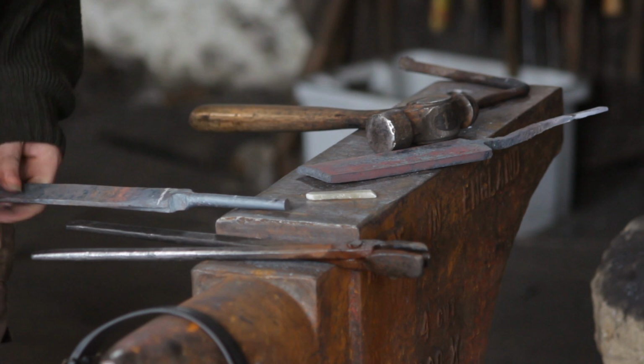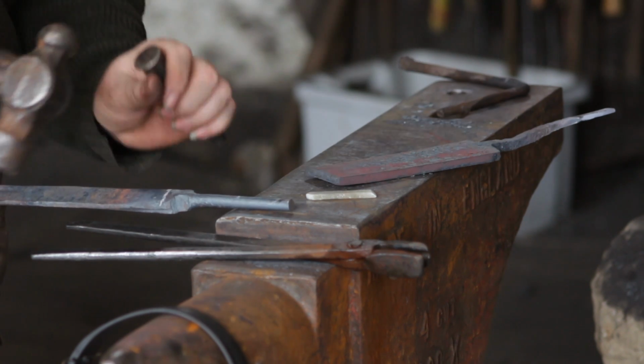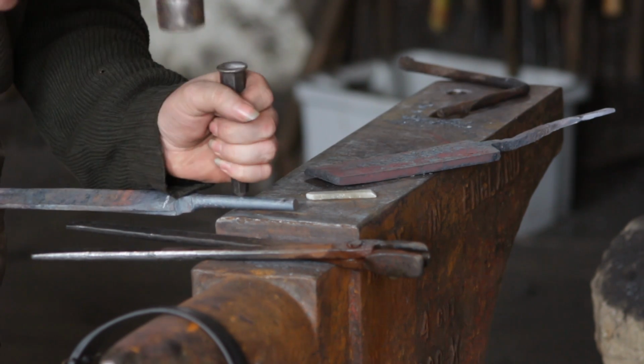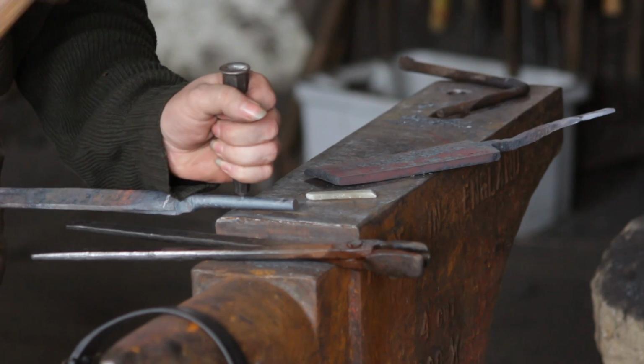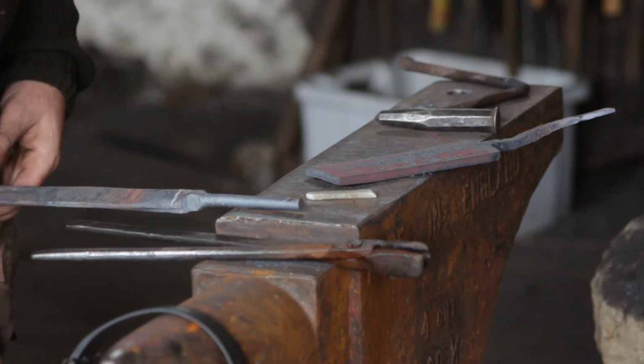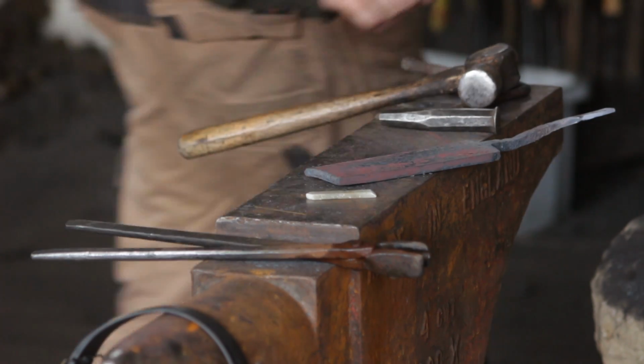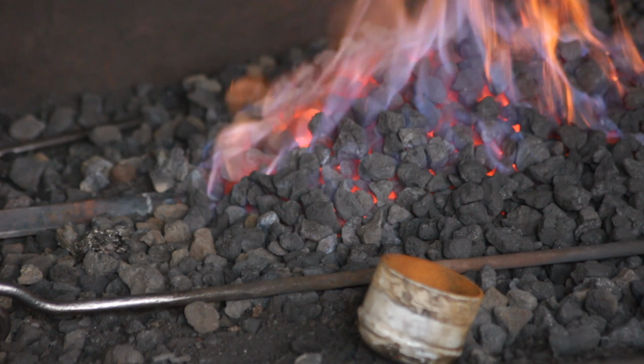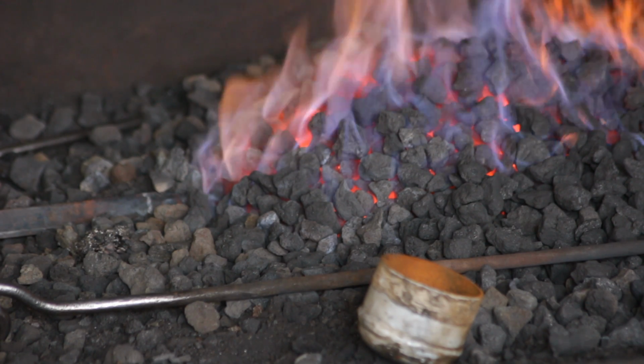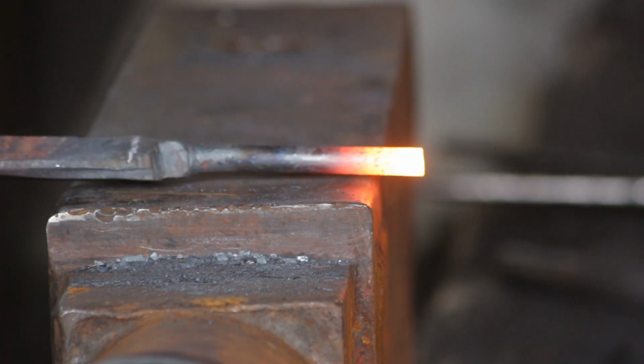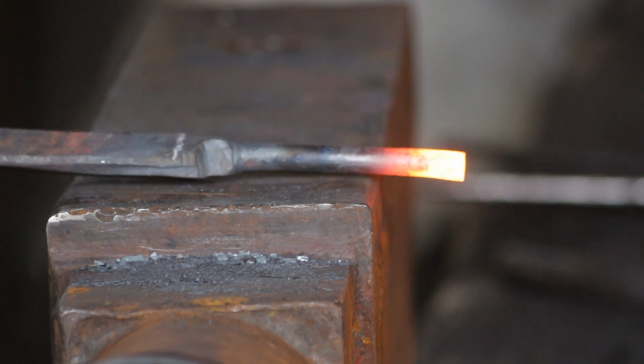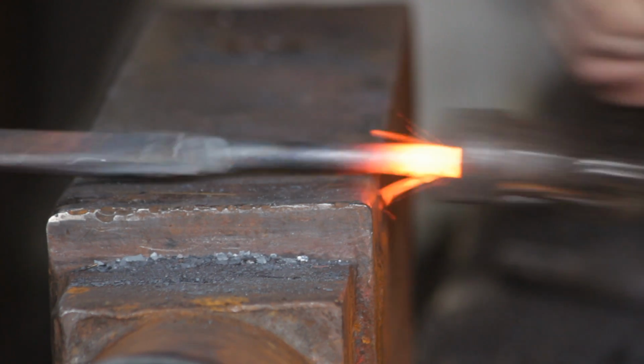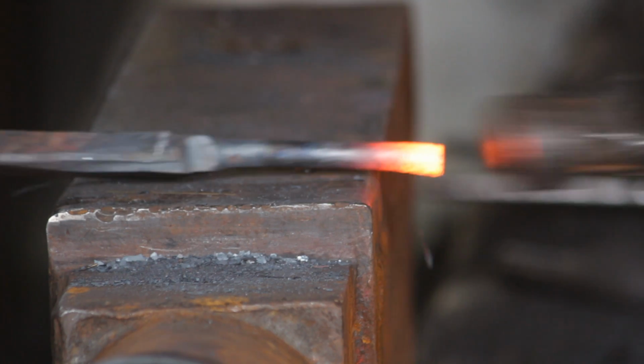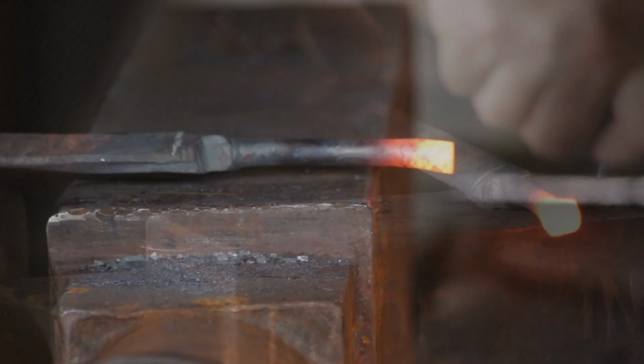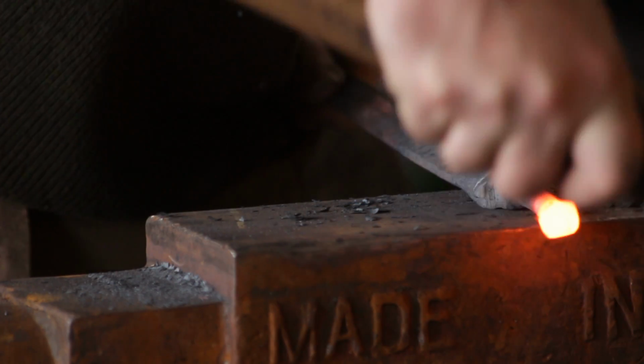Now the inner end of the upset, I will mark off discreetly with a centre dot, and that will save me upsetting too much beyond that mark. So it's all been cut down now, and this is carbon steel, so you want to be careful how you heat this. I take a while to heat it up, just to ensure that I don't heat up where I don't want to upset too much. Because obviously this is carbon steel, like I just said, so you don't want to be quenching it off to get a short heat.